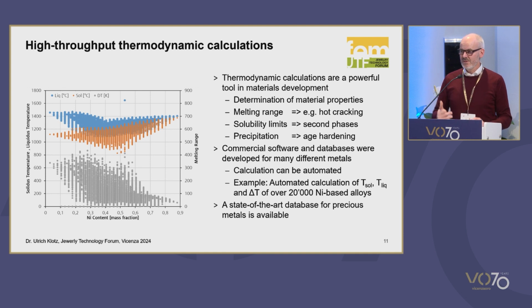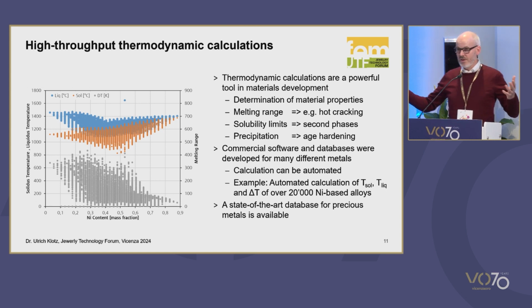And with a set of filters, we narrowed down these 20,000 alloys to about 10 alloys that we found interesting for further characterization. And then we melted these 10 alloys, but we screened a much wider range, and this gives us a much better feeling how the system behaves and what is the role of the different alloying elements.